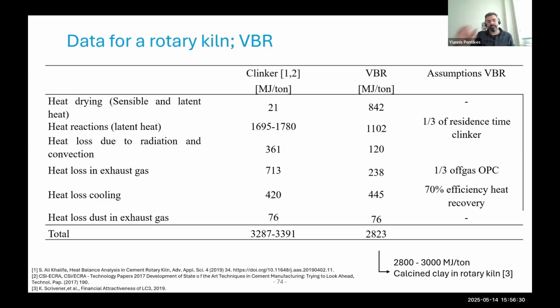And then we started going a bit deeper in the process, trying to analyze how sustainable it really is. Here you see things for the clinker production. You find the total energy needed, anything around 3,300 megajoule per ton. And here is our process, 2823. So that's nice. First checkpoint: we actually need less energy than needed to produce the clinker today. This is quite close to the energy needed to have calcined clay in a rotary kiln. Also nice, because calcined clay is now becoming the product for cements. These are the lime calcined clay cements, LC3. So we are on that range.